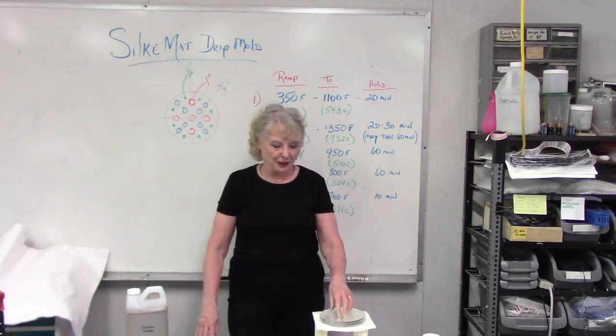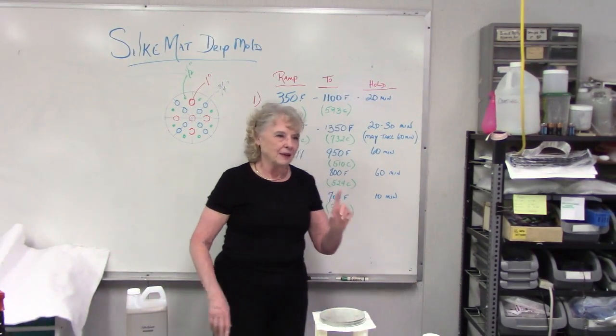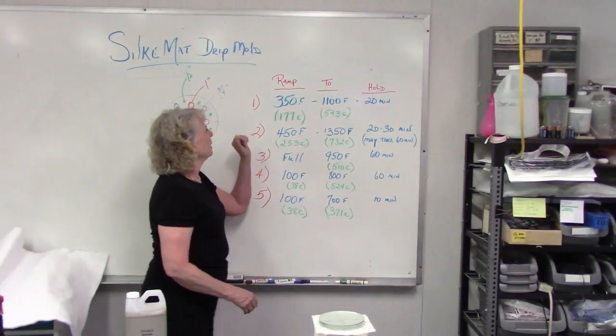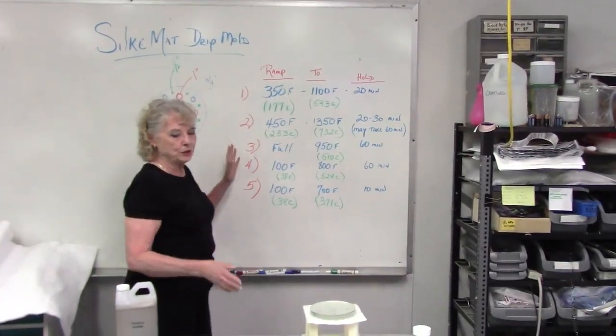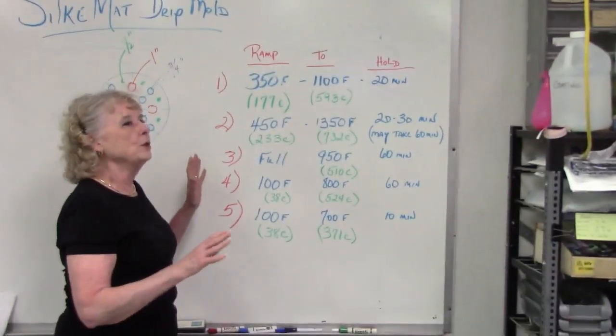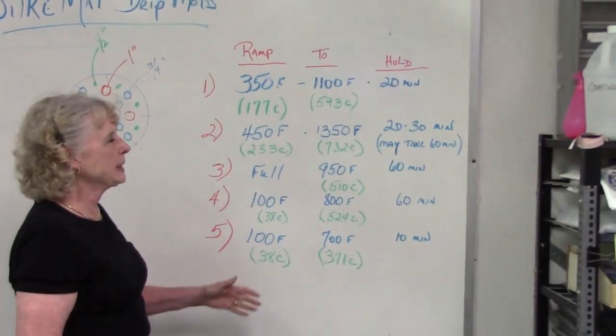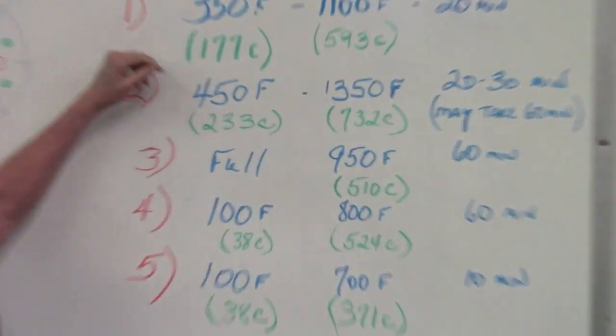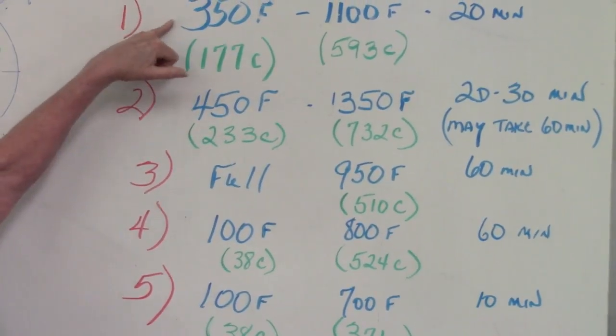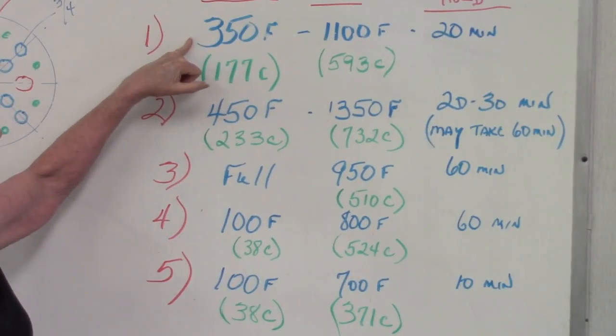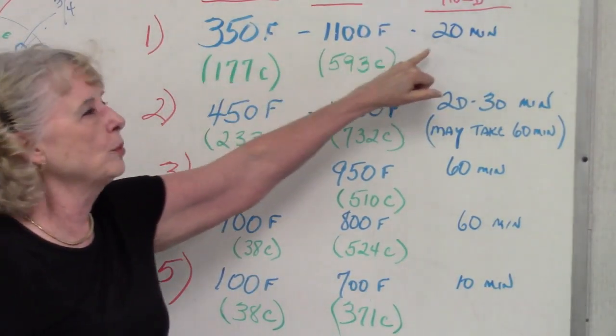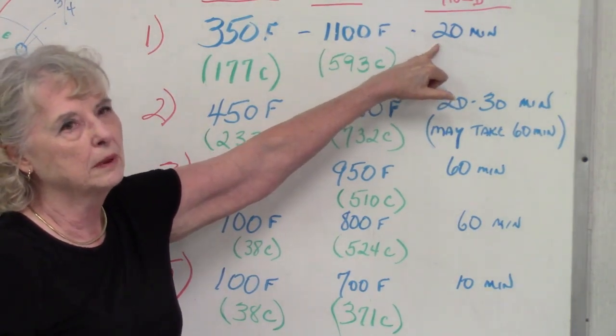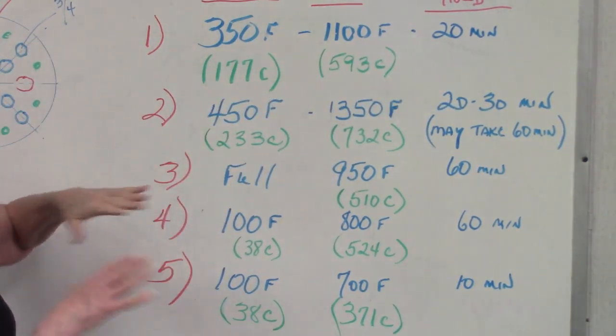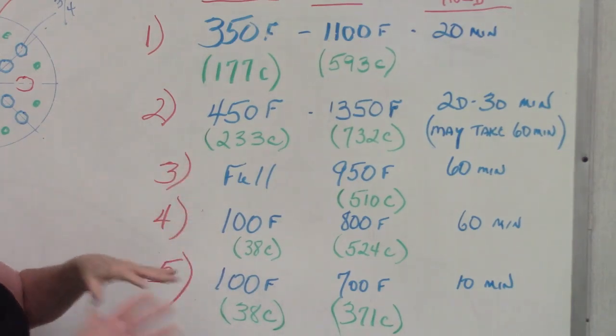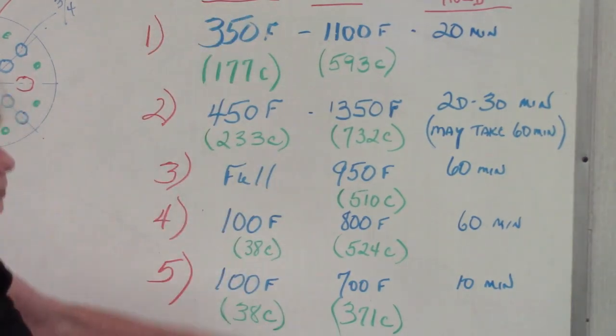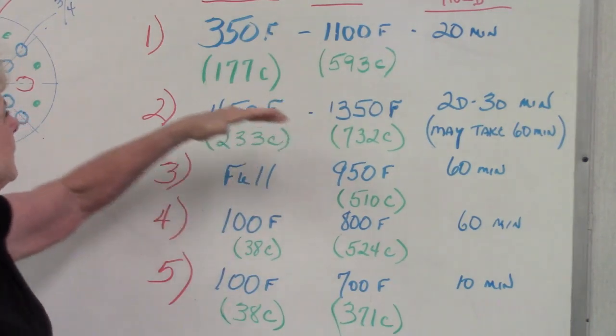So we've got this stacked up, ready to fire. All right? What's the next step? This is the schedule that I used for this piece. Yours can be completely different. This is only one of many schedules, but it's a place to start. So I started at a ramp of 350 degrees Fahrenheit to 1100, and I let it rest for 20 minutes. It's always a good idea to let your glass rest sometimes as it's changing its formation. I have Celsius temperatures down here for those of you who speak metric.